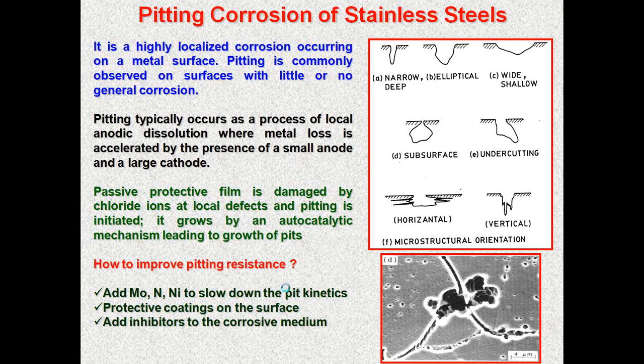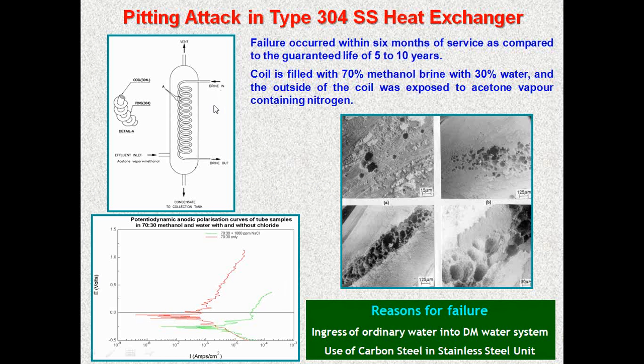I am giving you a small example of a 304L stainless steel cryogenic condenser, which is used for cooling. It is used to cool acetone vapor mixed with methanol, and it is cooled by a brine, and this is made of 304 stainless steel. Within a short time of about 3 months, there was a leaking attack at the coils. You can see the pits that are formed and that led to the leaking.